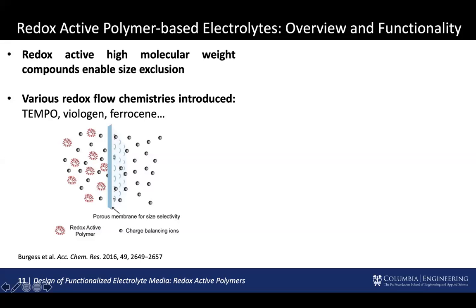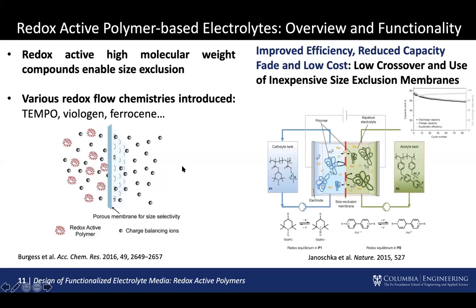So what that means is that if we have a redox species with a larger hydrodynamic diameter, so larger size, we don't need such a selective membrane to prevent its crossover. So instead of using something like an ion exchange membrane, we can use a dialysis membrane or a size exclusion membrane. And the first study that actually reported the use of these redox active molecules, they're shown here.